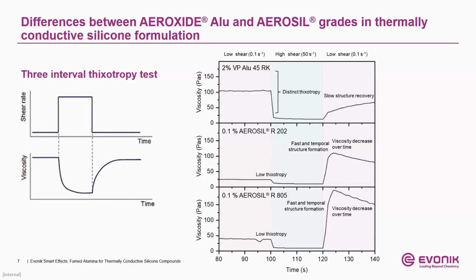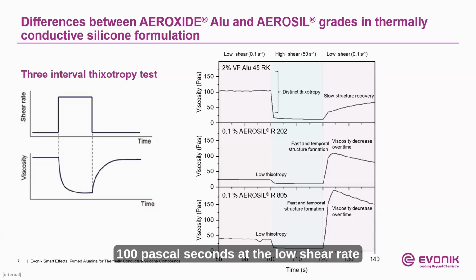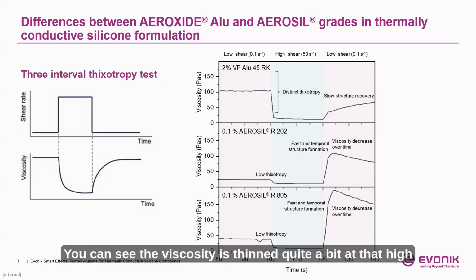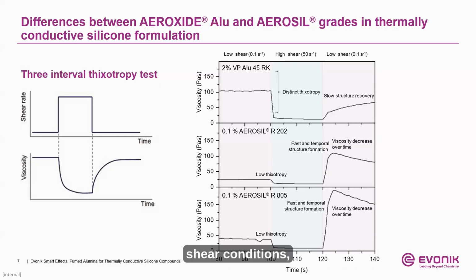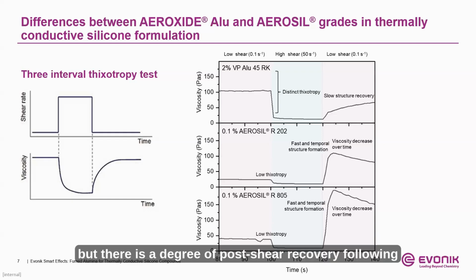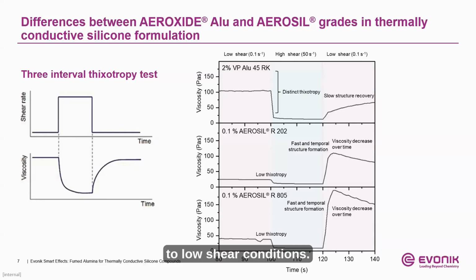You can see here it has a viscosity of about 100 Pascal seconds at the low shear rate condition. Then we see a significant shear thinning behavior following the distinct thixotropy, the gray area in the middle of the graph. You can see the viscosity is thinned quite a bit at that high shear conditions, and a bit of a slow structure recovery here, but there is a degree of post-shear recovery following that high shear condition when it is returned back to low shear conditions.